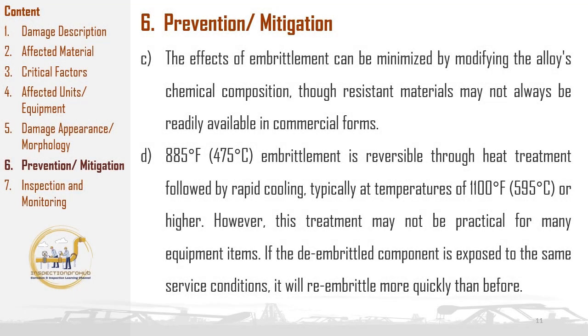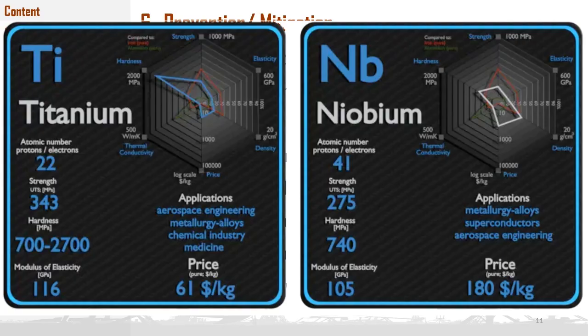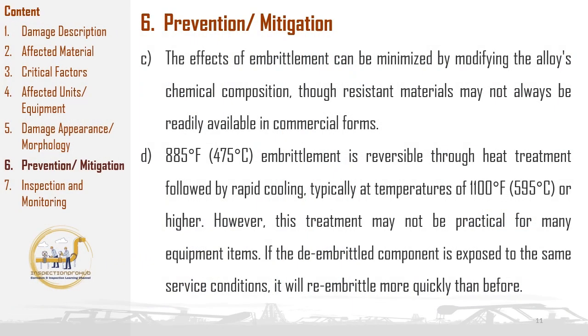The effects of 885 degrees Fahrenheit embrittlement can be significantly reduced by modifying the alloy's chemical composition, particularly by adjusting the chromium content or adding stabilizing elements like titanium or niobium. This approach can enhance the material's resistance to embrittlement at the critical temperature range. However, it's important to note that these resistant materials may not always be readily available in commercial forms, which can limit their application in certain industries or for specific components. This constraint necessitates careful planning and potentially longer lead times for material procurement.